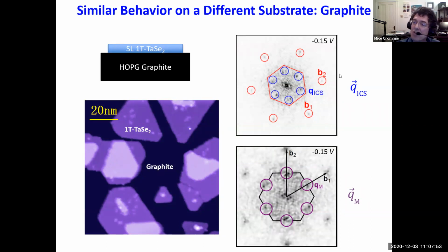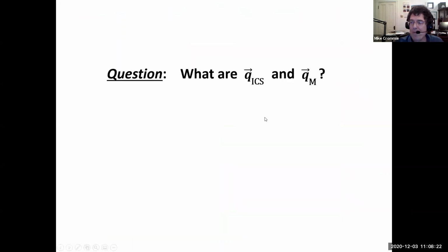Here's 1T-TaSe2 on graphite, HOPG, and you can still see these ICS features in the Fourier transform. But in addition, on the graphite, we saw another feature. We saw another long periodicity, which occurred at the M points of the Brillouin zone. I'm circling them in purple. And so we call that feature Q_M. That's the wave vector Q_M. So that's another periodicity that we saw for this material on graphite. Okay, so that's basically our experimental observation.